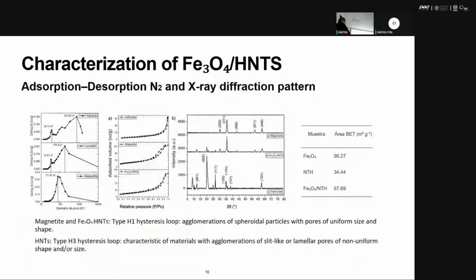Then I use the BET method to get the superficial area and to find the pore diameter. And even more, I use X-ray diffraction to be sure that all the signals of the magnetite and the halloysite are present in the material. In this result, I can see that the magnetite has a type I isotherm, which is common in agglomerated and spherical particles, and the halloysite has an H3 hysteresis loop, which is characteristic of materials with laminar and non-uniform shapes.